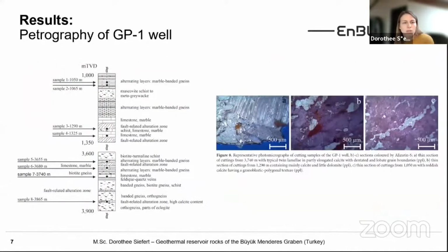So about the petrography of the GP-1 well, as I said, we drilled 2 marble horizons. Here, I did not present all wells, just the 2 parts of the well which are interesting. So to go from the depth, bottom hole, we had an orthogneiss with eclogite intercalations. And above this, the deepest carbonate-bearing rock section was sampled and further analyzed. It's a fault-related alteration zone with a significant calcite content. And above, we have a mixed layer of predominantly banded gneiss and orthogneiss.